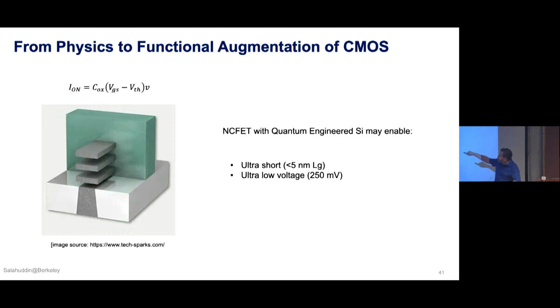If we can do really well, it will also let us reduce VTH. That allows us to reduce voltage. If you go to this very thin silicon, it increases velocity, it allows us to reduce voltage. If you go to very thin silicon, it allows you to reduce the channel length, and reducing channel length has a positive feedback effect, because if you reduce it smaller and smaller, the electron has to go a shorter distance to go from source to drain. That means its velocity can start to approach its ballistic velocity. That way its velocity goes up even more, which then reduces the voltage even more.